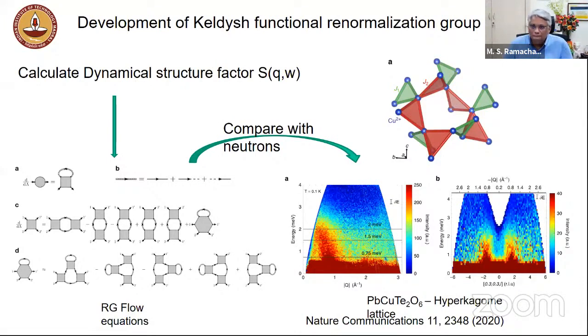So what you see out here is an example of one particular quantum spin liquid material candidate, lead copper tellurium oxide, which is based on what is a hyper-Kagome lattice. And you see the inelastic neutron scattering spectrum of it. So these are the type of spectrums which are modeled by these kind of formalisms. So you can see from here generically that theory and experiment go very hand in hand in this particular business of quantum materials. You have a theoretical model, you would use it, you would make predictions, and they have to be verified by experimental findings.